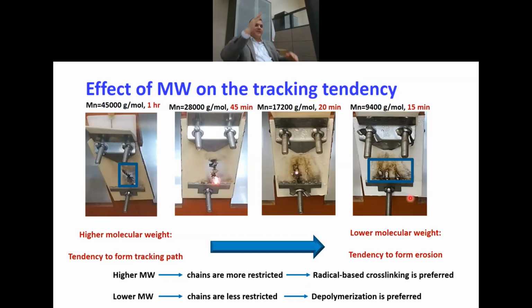In the case of butadiene rubber, the cross-linking happens across the chain. But in this case, it's end linking. We call it end linking, or it's not really cross-linking. You link the chains from the end. So the entire chain length will make a difference between the high molecular weight and low molecular weight. In this case, we have 45 thousand gram per mole between the two cross-linking points. But in the lower molecular weight, we have about 10,000 or 9,000 gram per mole between the cross-linking ends. But at the same time, the degree of cross-linking is much higher in the case of the low molecular weight, which restricts the motions.